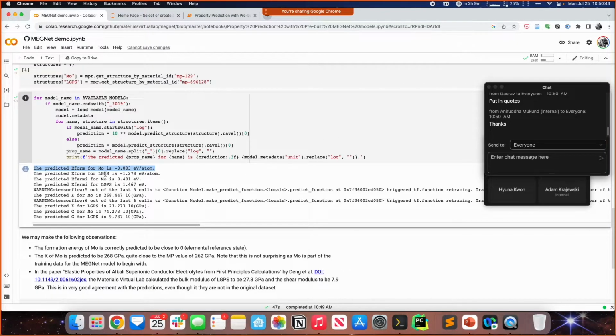Now, I'm going to ignore... LGPS has a negative formation energy, which means that it is exothermic when you try to synthesize it. The two properties that I want to show is here, right? So you see that the predicted bulk modulus for moly is 268 gigapascal, and the predicted bulk modulus for LGPS is 23 gigapascal, right?